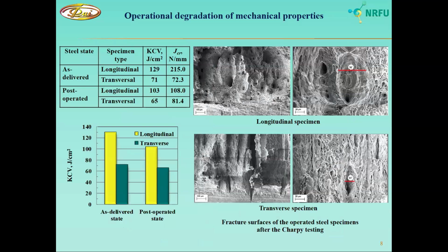A main feature of operational degradation of pipeline steels is a decrease in brittle fracture resistance. And we can see that impact strength and fracture toughness are significantly lower for the operated steel than for the as-delivered one, indicating in-service degradation of material. I'd like also to note that a detailed analysis on fracture toughness will be presented today by Professor Nikiforchin in another session for these steels.